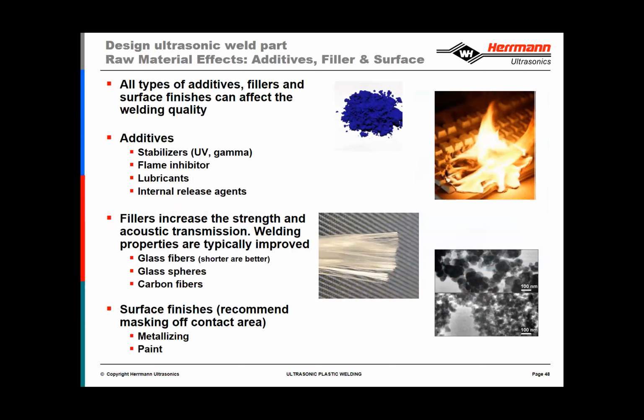Oftentimes, fillers such as glass fibers, glass spheres, or carbon fibers are added into a material to enhance the mechanical properties, the stiffness or the strength of the material. While on one hand, stiffening the material does certainly create better transmission of the mechanical vibrations, it, on the other hand, does reduce the amount of weldable material-based resin that's within the parts. That's not to say that we can't weld parts that have glass fiber or glass fill in them. We've very successfully welded parts that have up to 30% glass. The downside is that the glass can cause wear to the tooling.